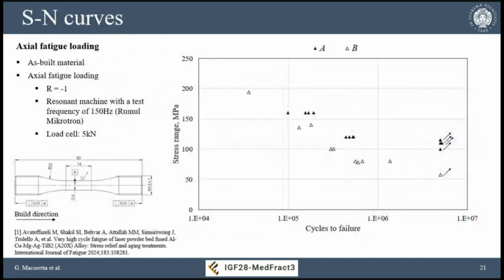If we move to fatigue testing, we carried out fatigue testing with a load ratio of -1, so fully reversed load, on a Rumul resonant machine using a load cell of 5 kilonewtons, with round samples of 6 millimeters diameter.